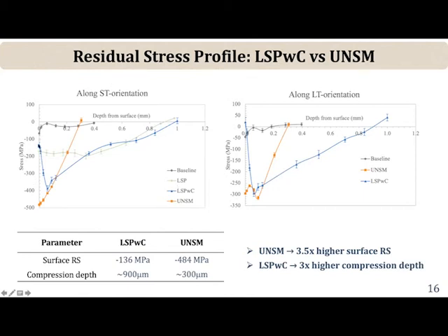The LSPWC, you can see the surface compression, because of the melted and recast layer, is much lower, but you can get fairly high levels of residual stress just subsurface. The depth of compression is much, much higher. And finally, in the case of the UNSM, you see that the surface compressive residual stress is much higher, but the depth of compression is much lower, okay?